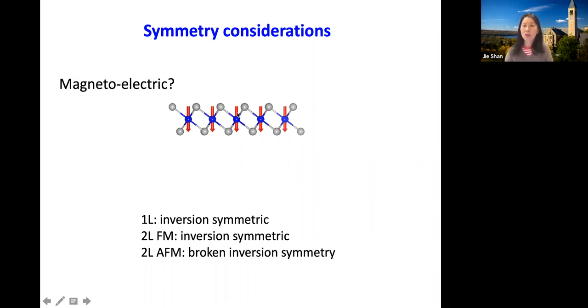So let's just take a look at the structure in the monolayer limit. If you don't consider spin here, the atomic structure itself has inversion symmetry. So I can just put my point here. You can go from this to that. So structure-wise, it has inversion symmetry. And in the monolayer limit, when you do inversion, spin down goes to spin down. So for the ferromagnetic monolayer, it has inversion symmetry.